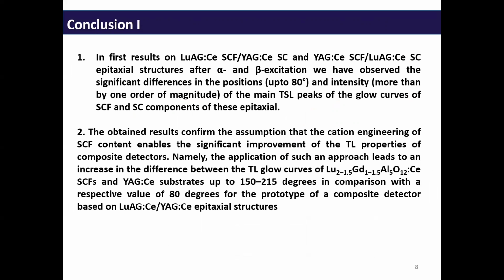In first results on lutetium aluminium garnet doped by cerium single crystal film onto YAG with cerium single crystal, and YAG with cerium doped single crystal film onto lutetium aluminium garnet with cerium single crystal epitaxial structure after alpha and beta excitation, we have observed significant differences in the position, up to 80 Celsius degrees, and intensity of the main TL peaks of the glow curves of single crystal film and single crystal components of this epitaxial structure.